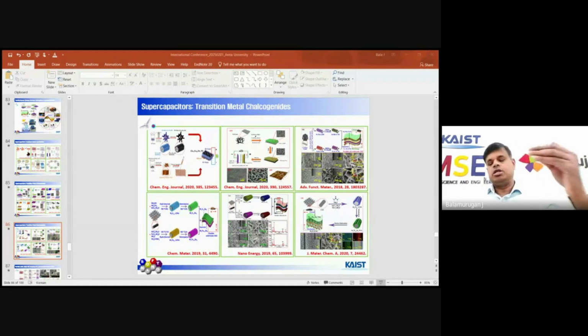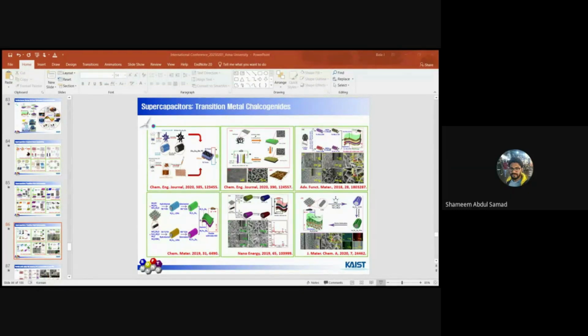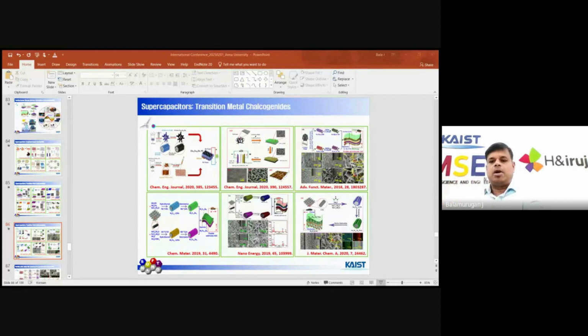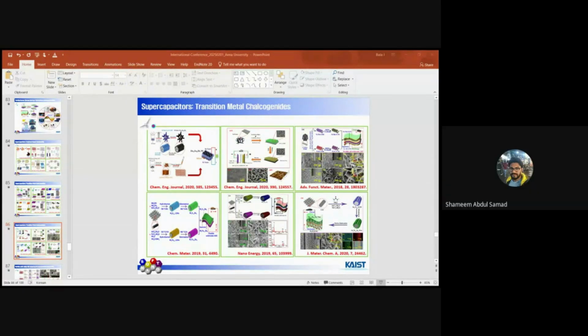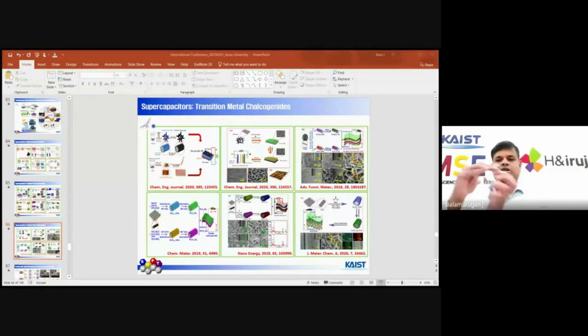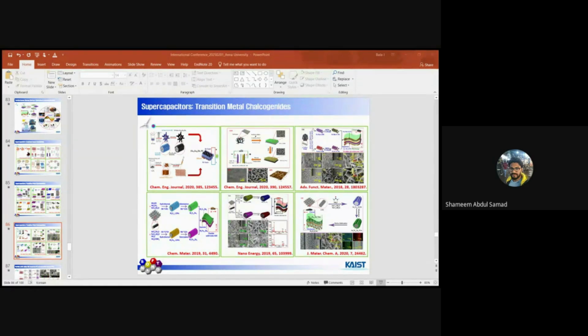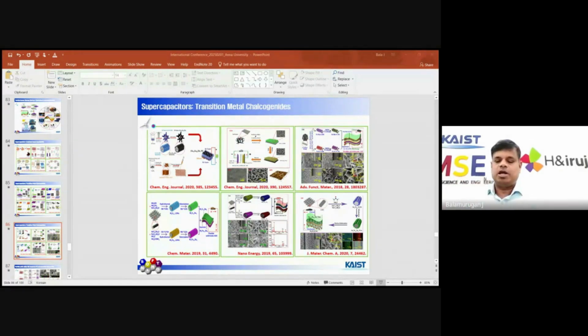First, we used powder based material, and even the powder based material was a graphene hybrid material, and we moved to nickel foam substrate and carbon cloth substrates. The material also we transformed from metal oxide, sulfide, selenide, and phosphate selenide based material. This is our transformation strategy of the material.